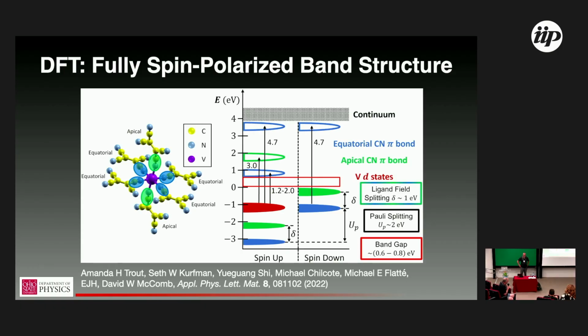But unlike something like gallium arsenide, where you might get a 0.7 eV band gap if you do a straight calculation, and its real band gap is 1.5, here the shift is a lot less, just because of this issue that the mass of the carriers here is so high.